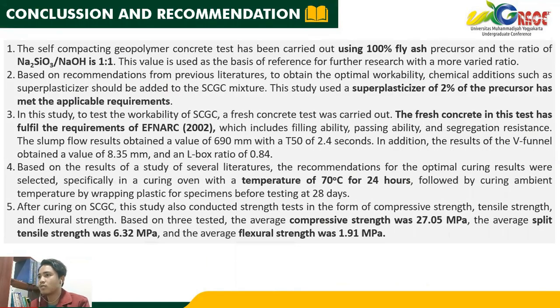So the last, conclusion and recommendation. The self-compacting geopolymer concrete test has been carried out using 100% fly ash as precursor, and the ratio of natrium silicate to natrium hydroxide is 1:1. This value is used as the basis of reference for further research with a more varied ratio. Based on the recommendation from previous literature, to obtain optimal workability, chemical additions such as superplasticizer should be added to the SCGC mixture.